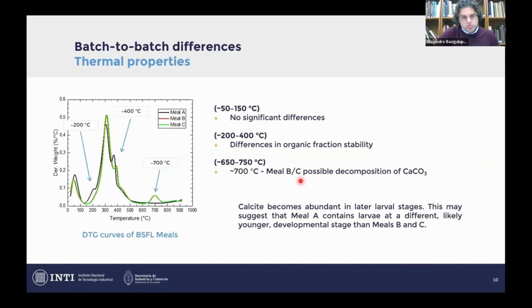Then we tried to get to know a little bit more of our meals. So what we did was thermogravimetric analysis, TGA. We studied the thermal decomposition of the three samples. And here we saw some very interesting results. For example, in the zone of the organic fraction stability between 200 and 400 degrees, we saw that sample A has very different stability than samples B and C. We can see here a little bit of a shoulder at 200 degrees, and near 400 we also see some differences in the thermal decomposition.